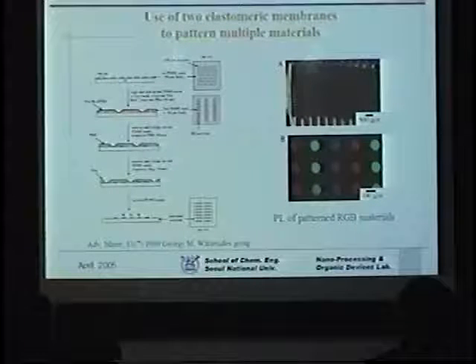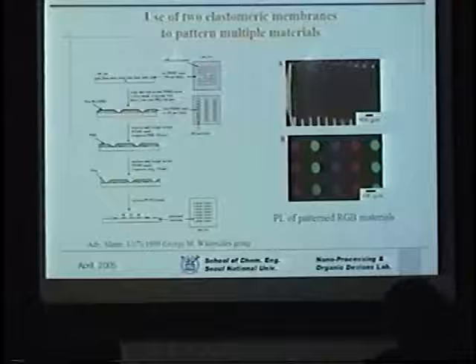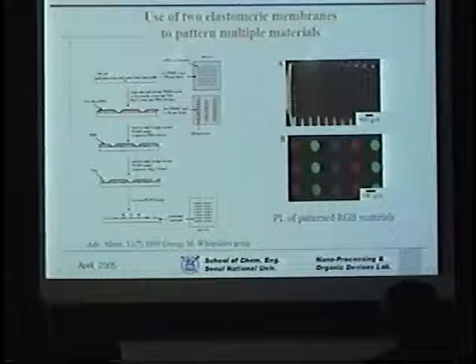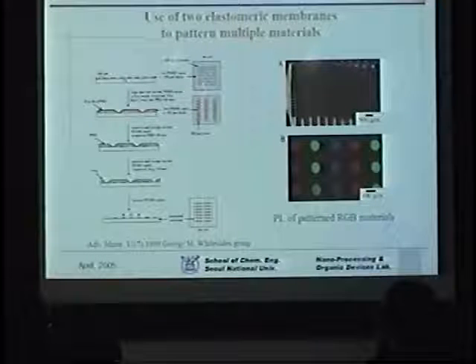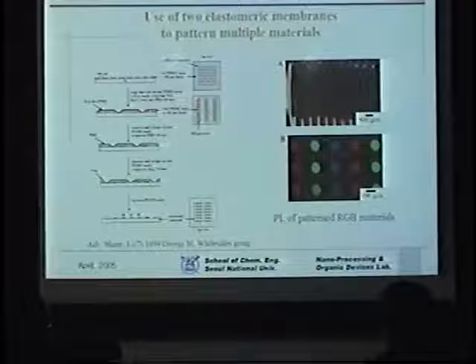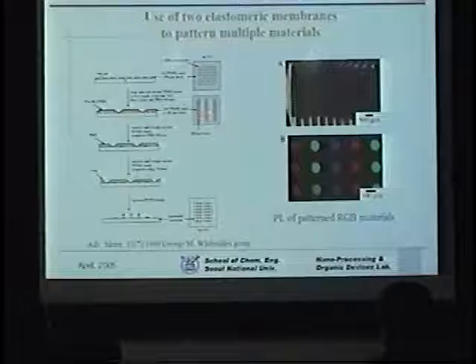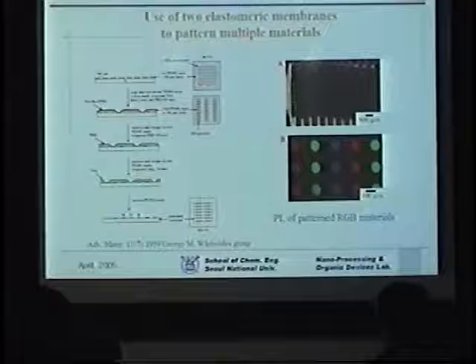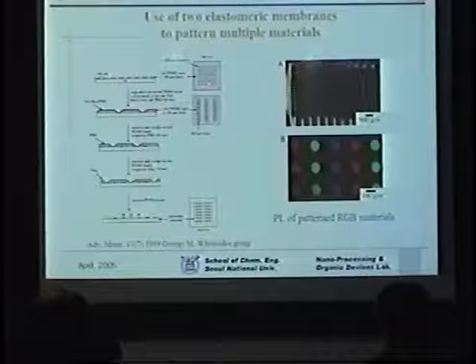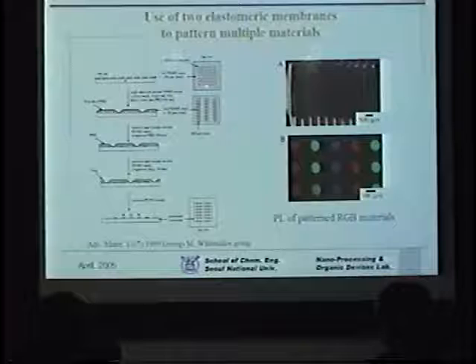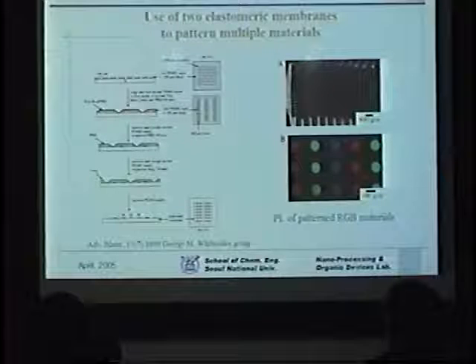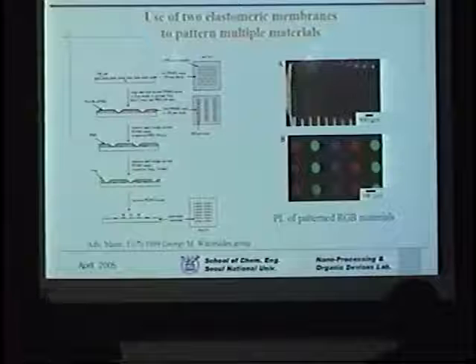They in turn turned around and saw how you can do RGB. In this case you have the same perforated membrane as before, but use another PDMS mold with the 9 openings. And you place this one onto that one, and that'll give you this kind of shape, that is the holes lined up along the line. In this case, you deposit R material, red material, and then you shift it a little bit in this direction for the G deposition, and move it again, and then to blue deposition. That way, you come up with this kind of RGB configuration.